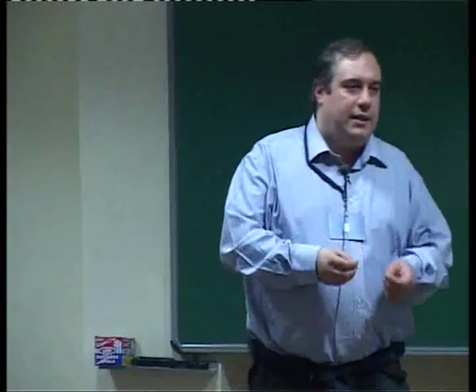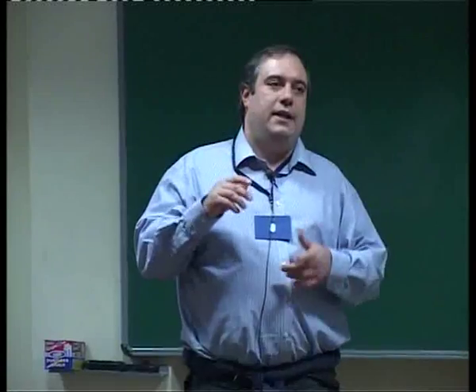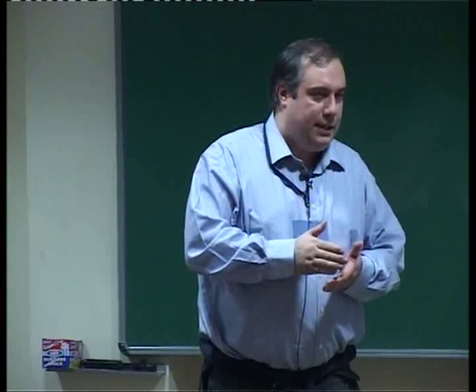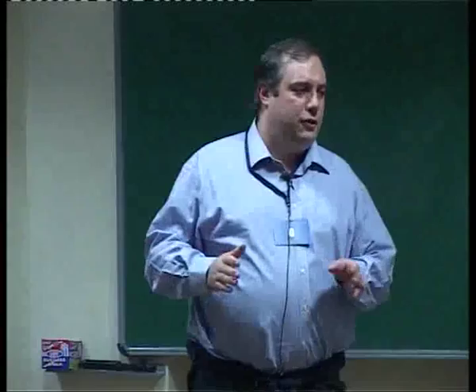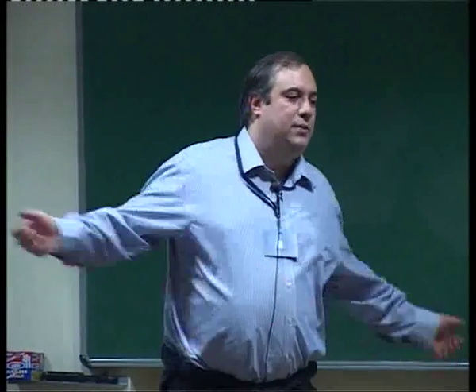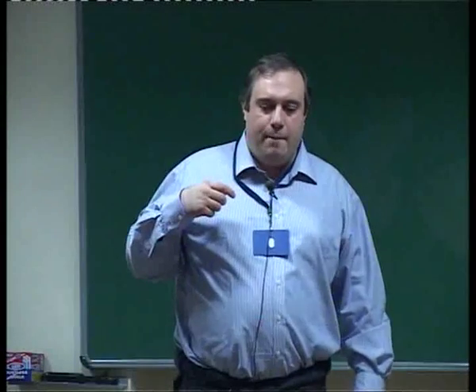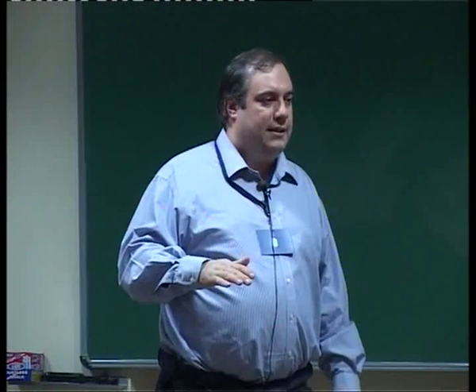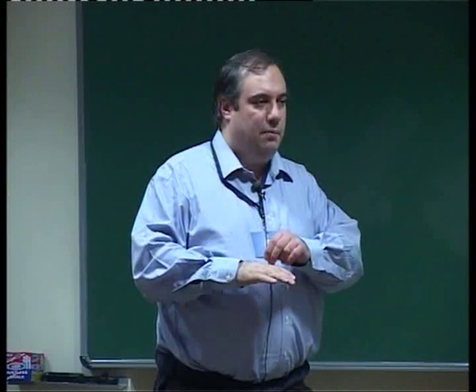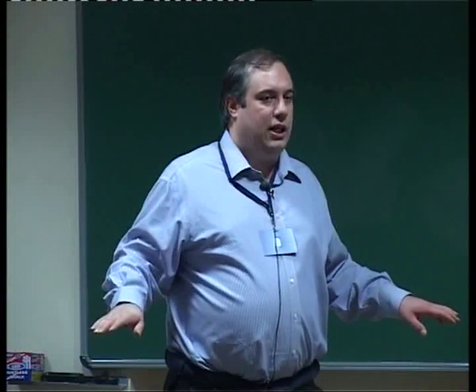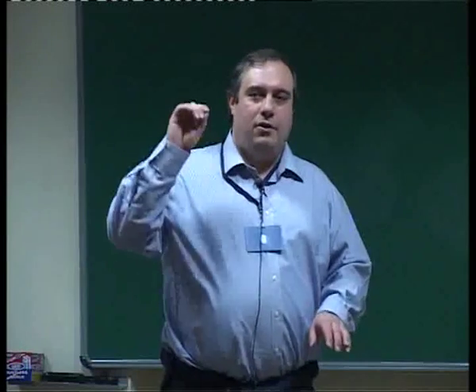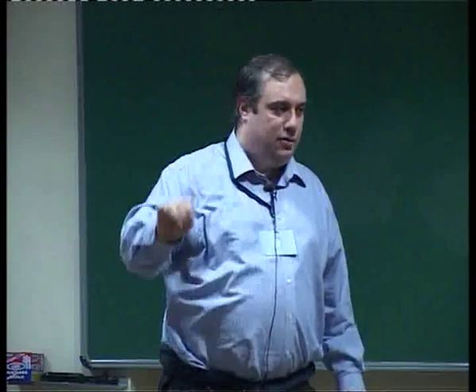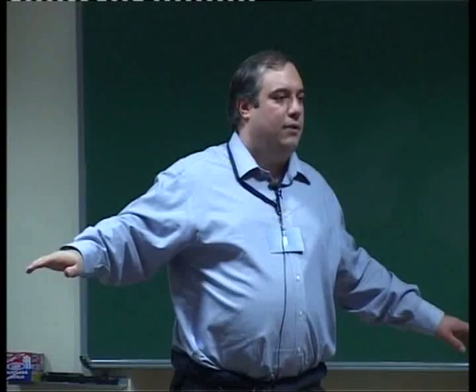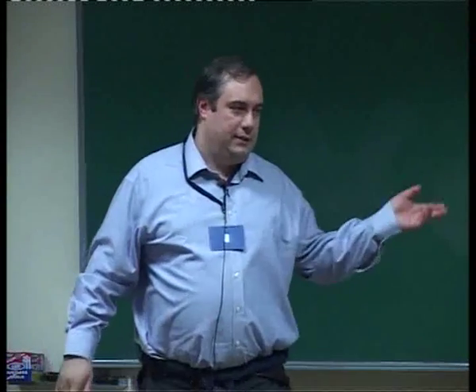Second trick, you take a nanocrystal which is semiconducting, like lead sulfide or something like that, and in this case, you have to be in resonance with the crystal. These crystals have a huge interaction with light, so they generate a lot of electron-hole pairs, but graphene can sweep them away. In fact, graphene is so good that graphene is suppressing photoluminescence when you put these nanocrystals on the top, because it sucks out all the charge carriers. So in this way, you get the nanocrystal to create electron-hole pairs, and graphene to take them out very quickly. And in fact, the responsivity, as I showed, is huge.